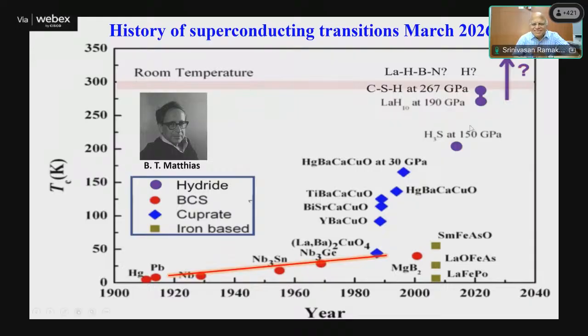The only exception is these hydrides. Hydrides were predicted. Actually, metallic hydrogen under heavy pressure is supposed to show superconductivity close to room temperature. Nobody could get metallic hydrogen and make it stable at such high pressures. So instead of looking at hydrogen, they looked at hydrides and then found superconductivity at very high temperatures. 250 Kelvin, 260 Kelvin is the lanthanum hydride. That seems to be the record at high pressures.